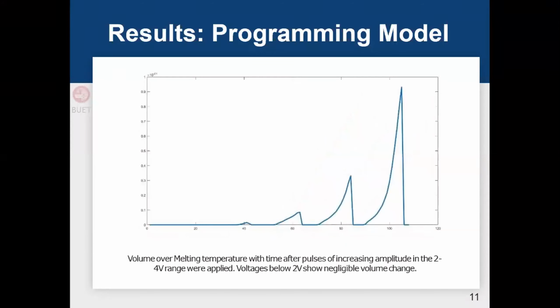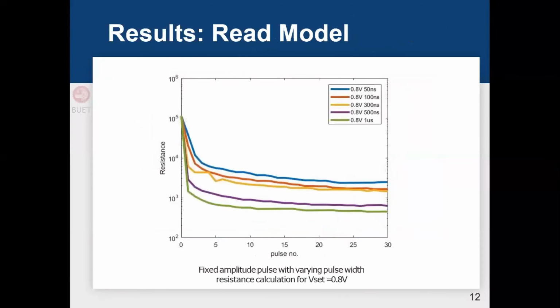And in this case, we have actually used a staircase type of pulse that has its amplitude increased from 2 volt to 4 volt. And initially, when there is a 2 volt pulse going in, the volume of GST over the melting temperature is too low. Whereas as we move forward to 4 volts, the volume of GST over the melting temperature is actually dramatically increasing.